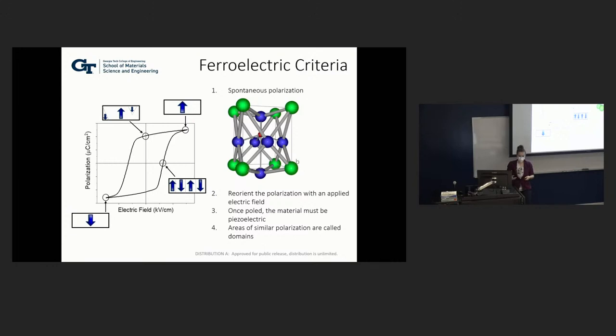Now, the thing that's really unique about ferroelectrics is that if you apply an electric field in the opposite direction, you can actually change the crystal structure. You can switch the direction of your dipole. You'll take this titanium that you have here, and instead of bonding to the top oxygen, you can drive it towards its bonds, towards the bottom oxygen. So it's an electric field-induced crystal structure change, which is pretty fascinating and rare.